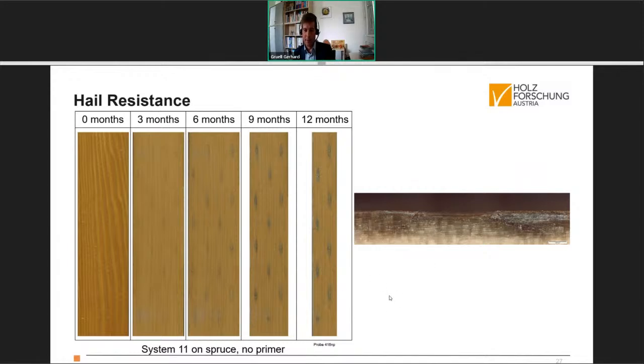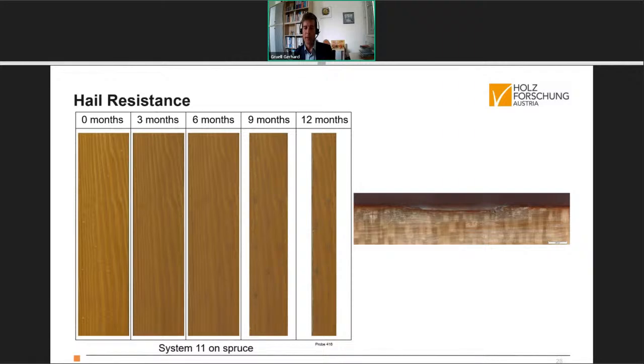We have seen that good primers and systems, including good primers, can really improve the situation very much. They can improve the tolerance of systems to hail impacts for a very long period. As you see here with the system on spruce, there is much less discoloration around the hail impacts after 12 months of natural weathering compared to the same system without primer on the first slide. And in the microscopic section, hardly any fungal growth here in the region under the hail impact.